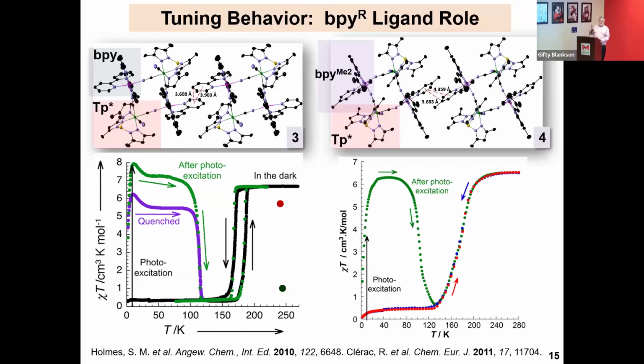We decided to substitute the bipy rings and put methyl groups on there to disrupt this pi-pi stacking interaction between rings on adjacent molecules. We purposely chose putting methyls at the 4 position because it doesn't change the electronic donor properties of the bipys, but might impact the intermolecular communication between them. While it's difficult to see, at least on that screen, you might be able to see it here. Basically, this is a very close contact here, and for here, these are slipped with respect to each other, slightly elongated. And that little difference makes all the difference.